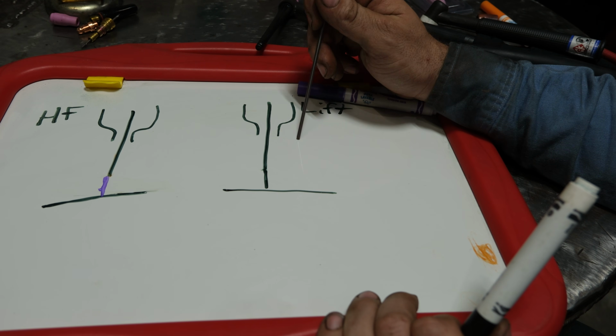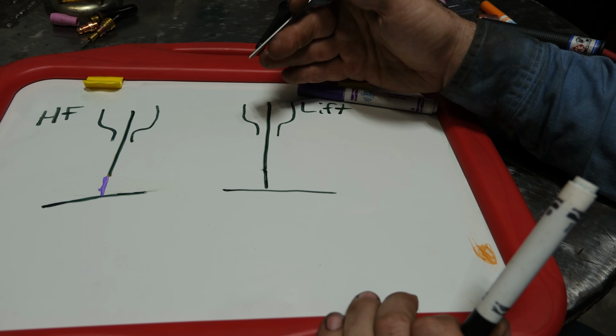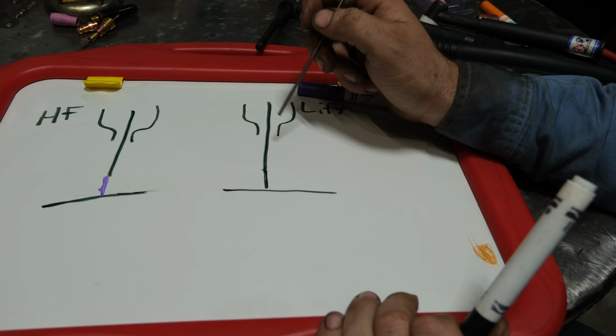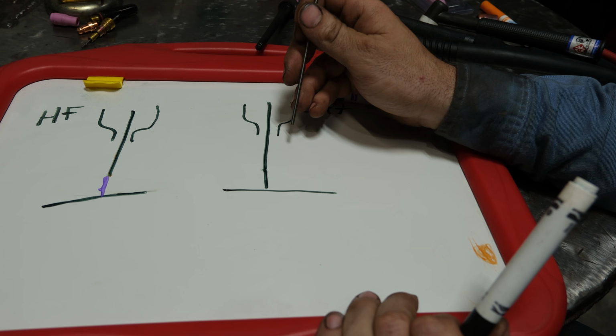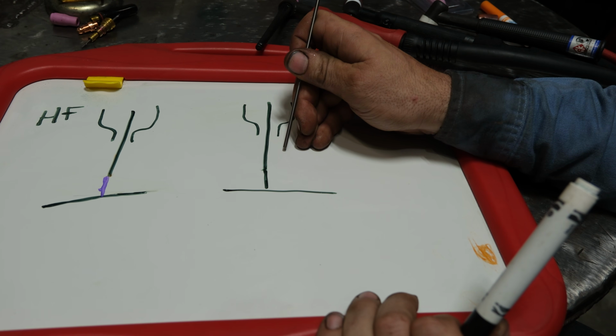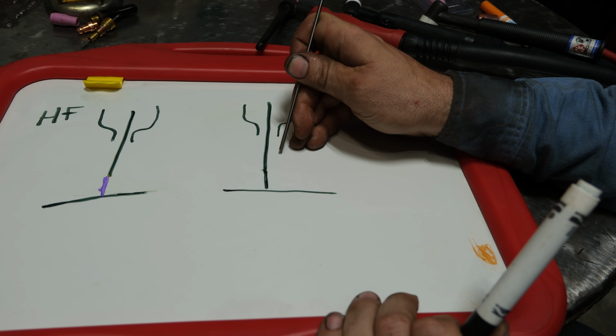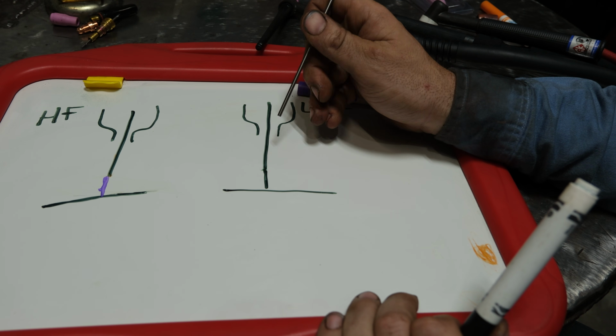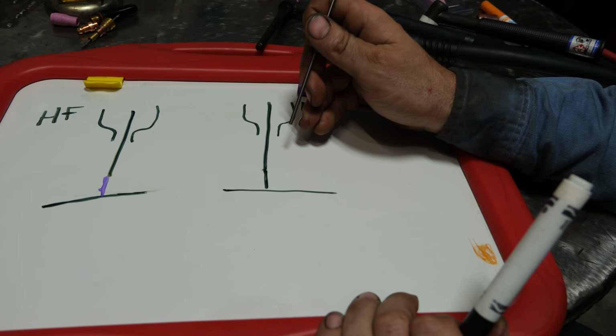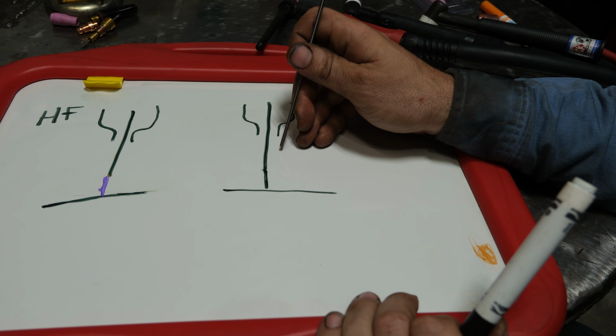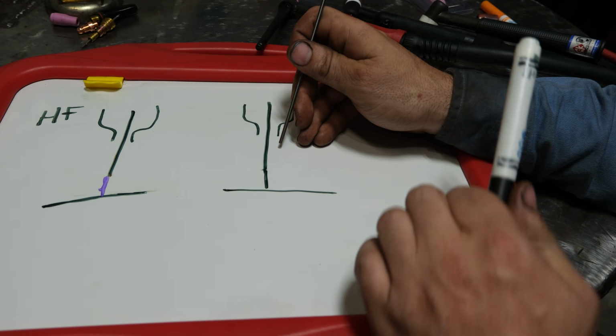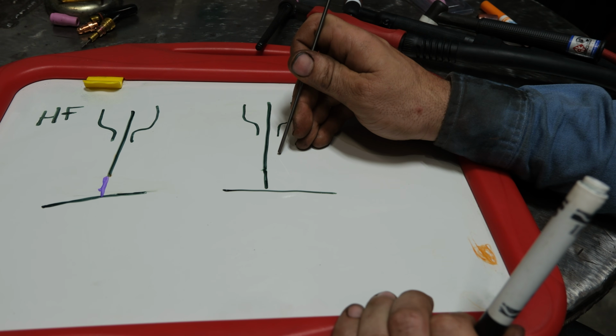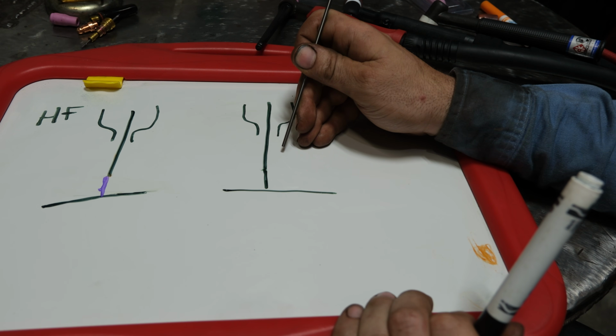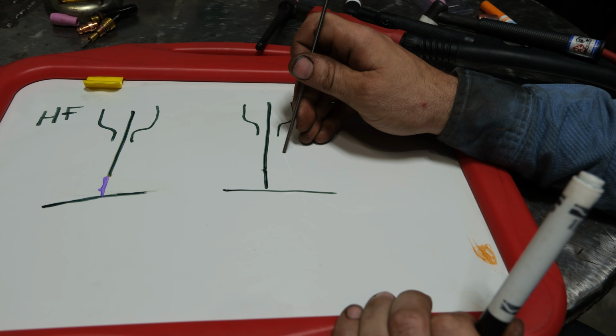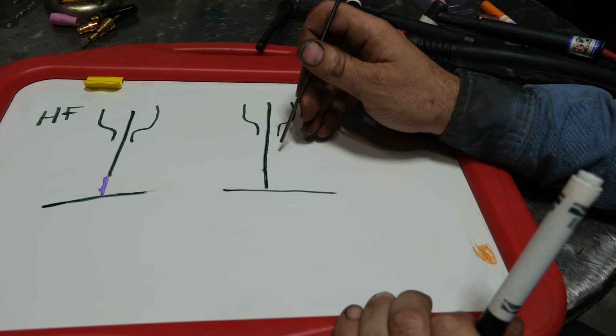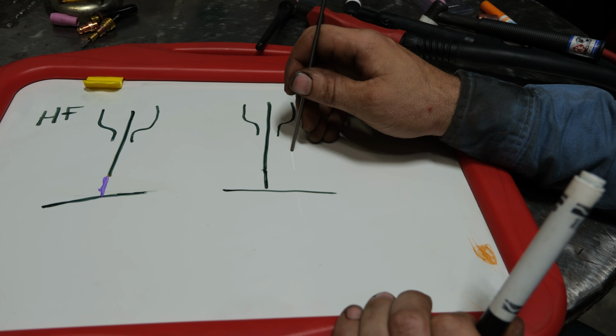Now, the third method to start a tungsten, besides dipping it in the molten pool, is what's known as scratch start. If you're familiar with stick welding, it's the same concept. You bring the tungsten down, and in one motion, you touch it, lift it, and the arc starts. So it's just like a stick electrode. Massive downside to that is because you have full power live at that tungsten tip at all times, when you come down and touch that and then lift it, what can end up happening is it welds itself right to the plate if you're not quick enough. Just like a stick electrode can be stuck to the plate, same thing can happen with the TIG tungsten.